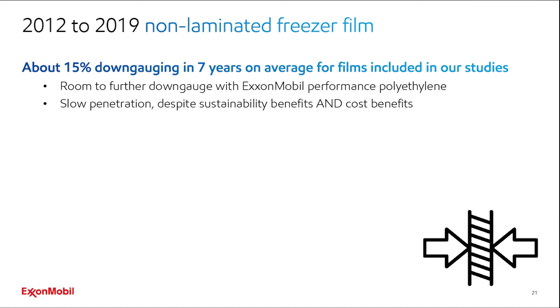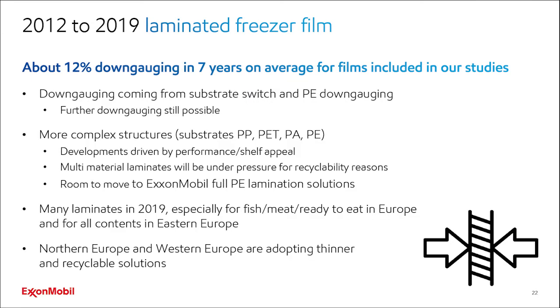Now, if we compare the results of 2012 versus 2019 for laminated freezer films, similar comments: downgauging did occur, on average 12%, based again on the samples that we collected in 2012 and in 2019. The downgauging is coming from 2 elements. The first one is the substrate switch. In 2012, the main substrate was PP, with an average thickness of 21 microns. In 2019, the main substrate is PET, with an average thickness of 12 microns. The second element explaining the downgauging is that the PE layer has also been downgauged over time.